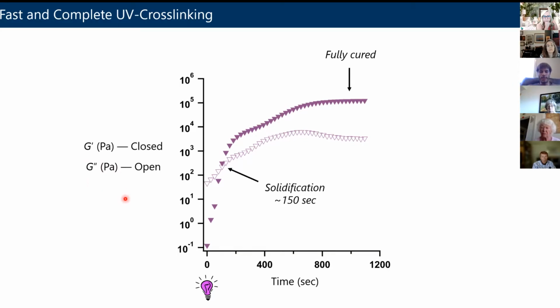And the key point is that at time equals 0 here, you have G double prime, that viscous contribution, much larger than G prime, that elastic contribution. This is a hallmark of a liquid. And that's what we just argued you have until you shine light on the material.